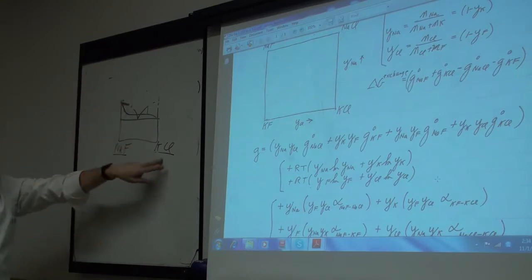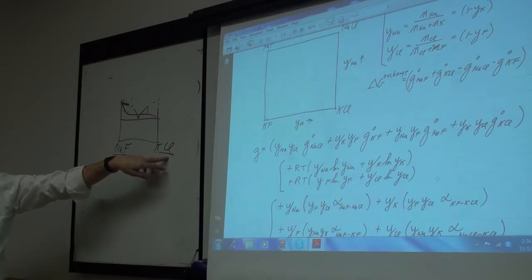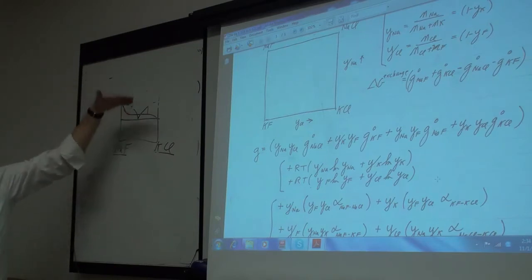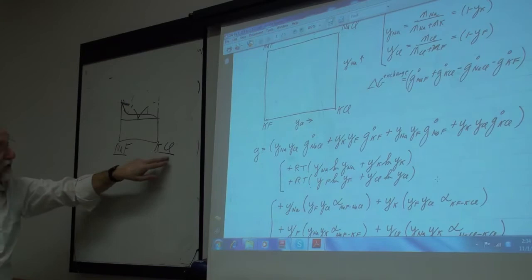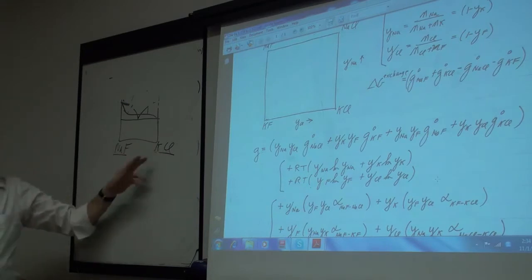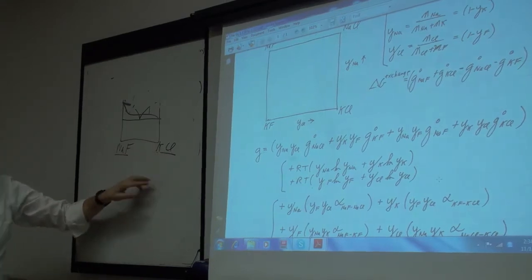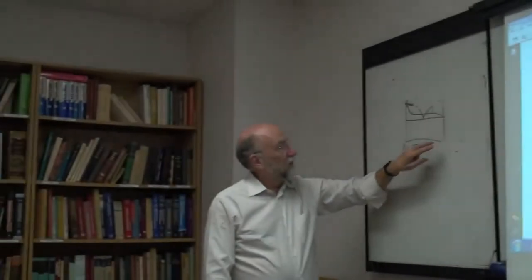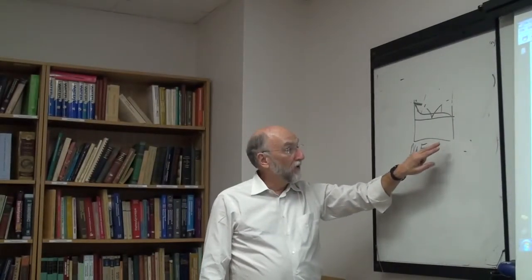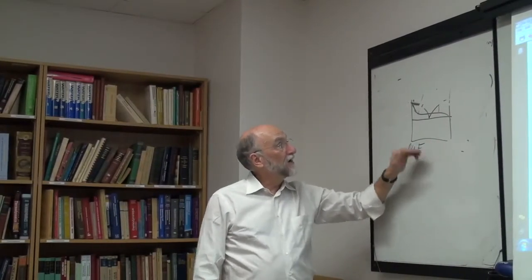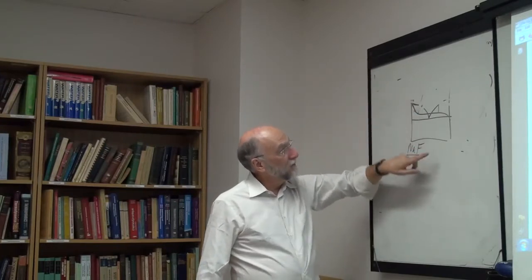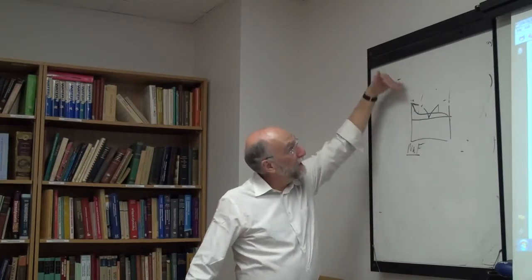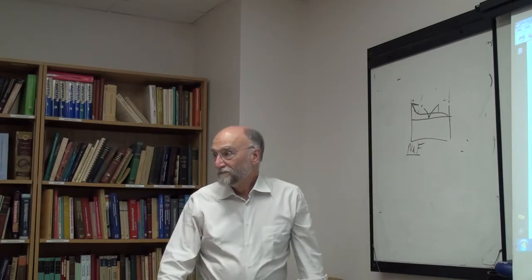Remember, we talked about it: it doesn't matter what the solute is. As long as you have no solid solubility, your limiting slope's the same. As long as you also have the same number of new particles coming in. So if you take NaF and you replace it by KF, LiF, whatever, or NaCl, NaBr, as long as there's an ion in common, you'll always get this slope. If you replace it by a salt which has two different ions, you get twice the slope.